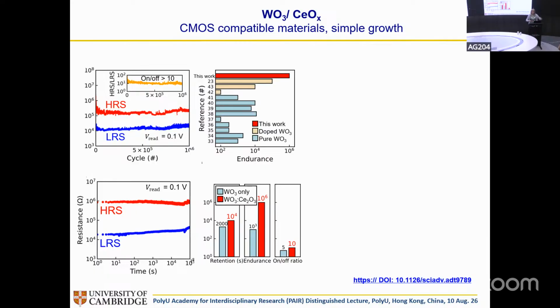And you can say, well, they're better in the literature if you tune other things and you put other layers in, but actually this is a very simple, one-shot single layer film. And furthermore, it's CMOS compatible materials. And furthermore, we understand what you need to do to improve this tungsten oxide. The tungsten oxide in the literature and then our tungsten oxide, what we've shown is that you need to have the reservoir, you need to have these confined filaments. So we get better retention and endurance than other reports, if you compare just single layers.